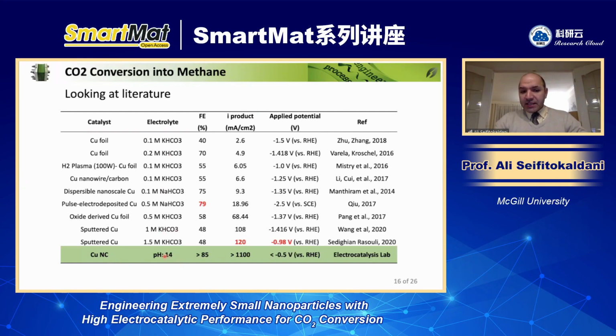we were able to utilize an alkaline environment and still not produce ethylene. Just a reminder again, the problem with using pH 14 is that people just promote ethylene production, but we were able to suppress the ethylene completely using this type of catalyst and achieve very high partial current density. This one is actually larger than 1200 milliampere per square centimeter, the number in the table is a typo. And more importantly, after converting the applied potential to the RHE scale and also considering the ohmic resistance, the applied potential versus RHE is less than what we had before.